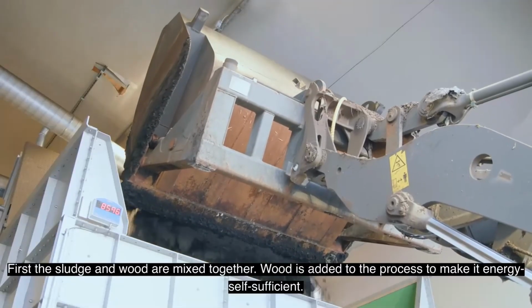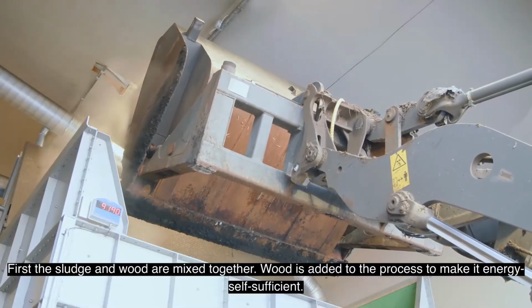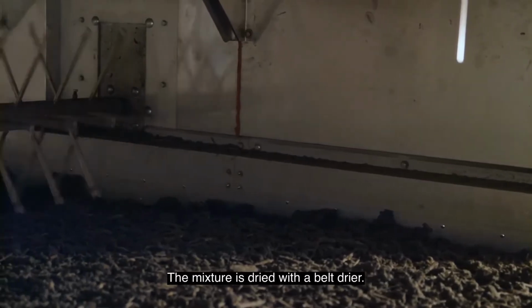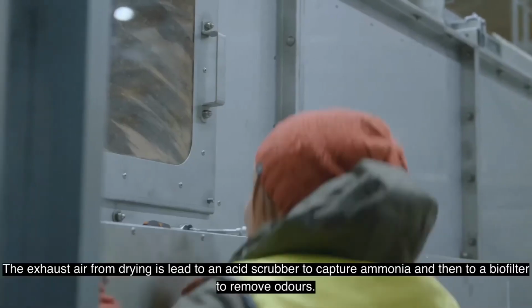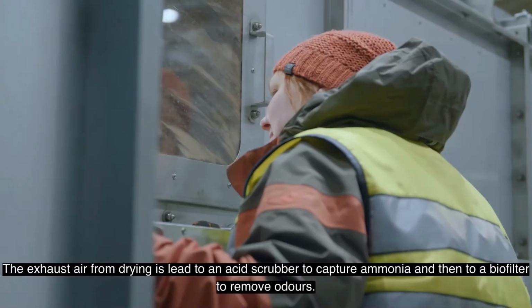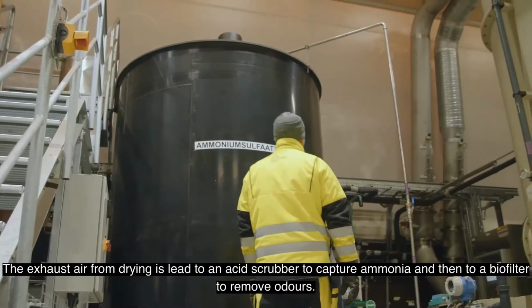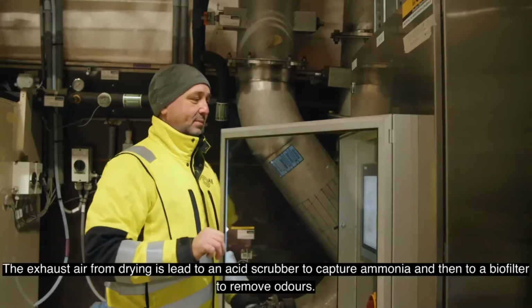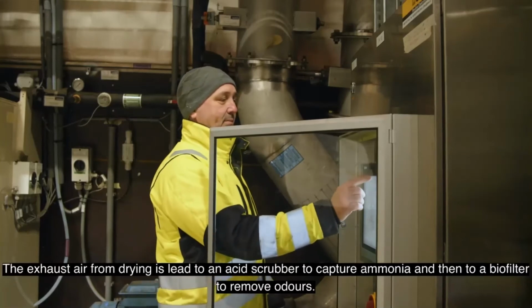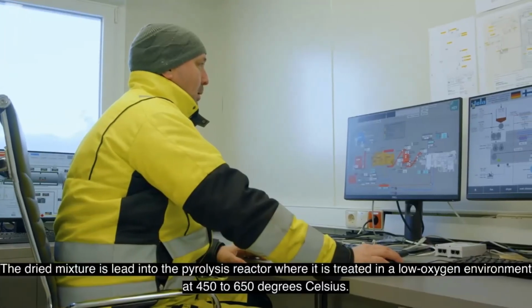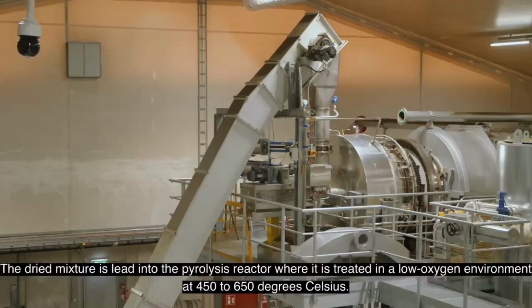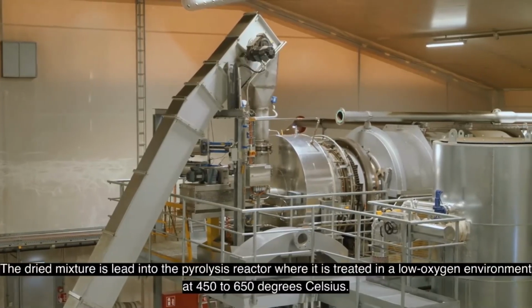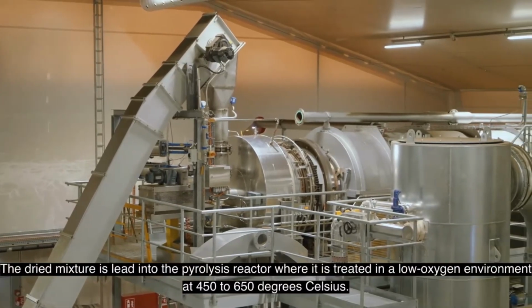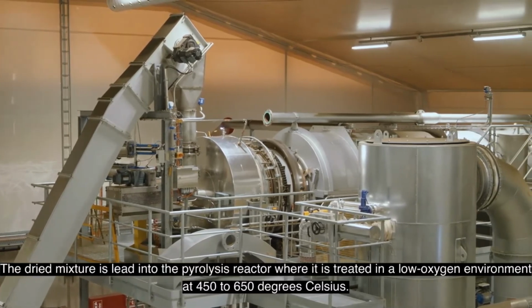Wood is added to the process to make it energy self-sufficient. The mixture is dried with a belt dryer. The exhaust air from drying is led to an acid scrubber to capture ammonia and then to a biofilter to remove odors. The dried mixture is led into the pyrolysis reactor where it's treated in a low oxygen environment at 450 to 650 degrees Celsius.